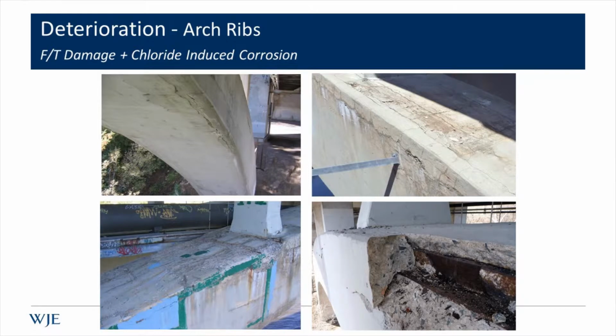And so the photo on the upper right, there's both chloride-related corrosion of the angle and then some freeze-thaw damage, a little more advanced freeze-thaw damage in the lower left below an expansion joint. And as those conditions combine and you get spalling of that corner, you can see the exposed corrosion of that double angle of the Melan truss in the lower right. But with the arch ribs, it was generally freeze-thaw damage and chloride-induced corrosion.